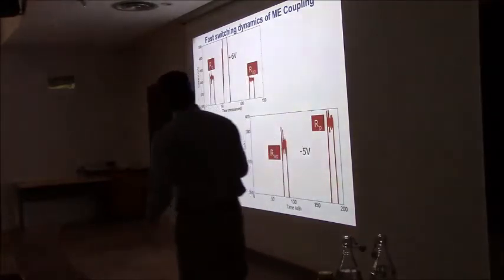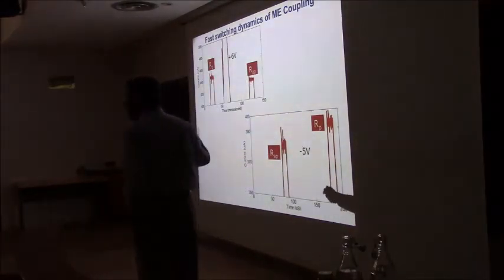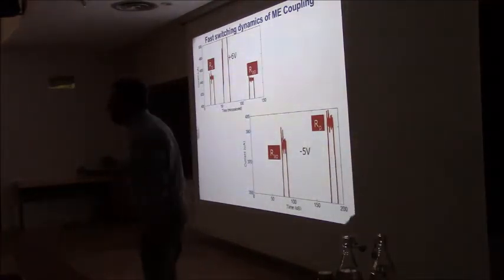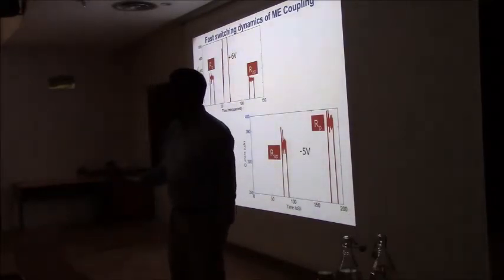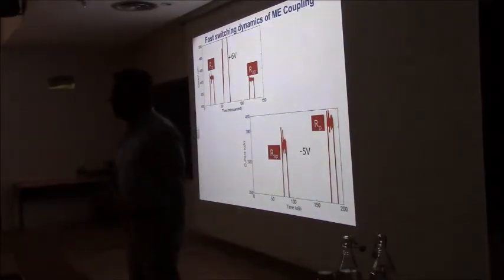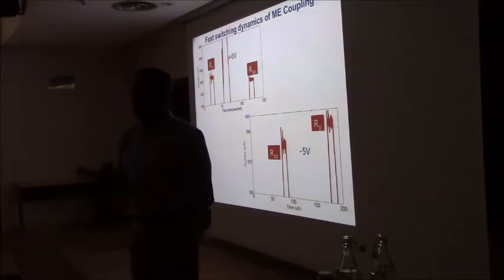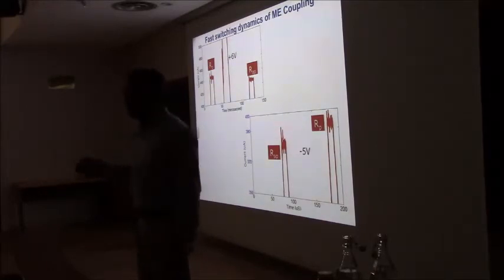And again, we also know that the magnetoelectric coupling happens very quickly. By the way, the dynamics of the magnetoelectric coupling, both within bismuth ferrite and coupling to a ferromagnet, is still not well understood. There are not too many measurements. This is a very rich space. If you can do ultra-fast measurements, that would be valuable.